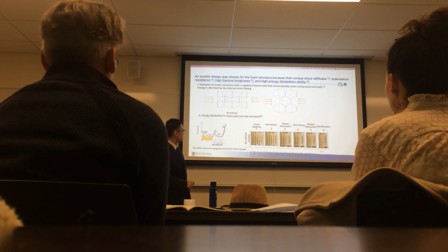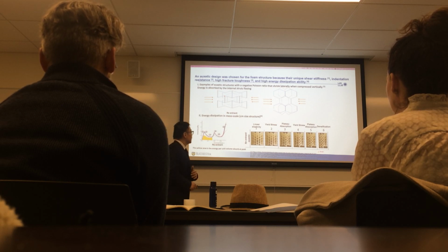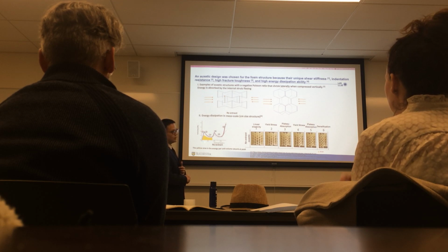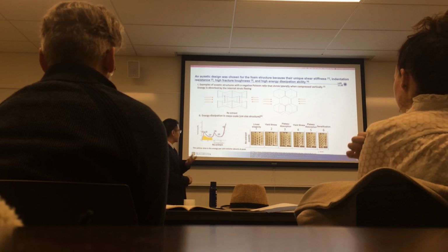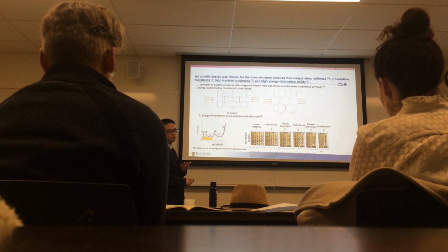For the auxetic structure, we compress the foam structures and get a stress-strain curve. Because we will use a similar experiment process, I want to briefly introduce how the stress-strain curve works. At first, the foam structure is linear elastic. From plot 1, it's a straight line, and from the straight line we can get the elastic modulus of the foam structures.